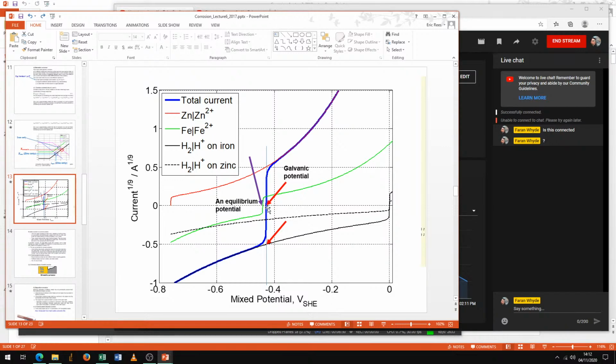That's just Le Chatelier: the ongoing net anode or net cathode process, if there is one, tends to go forwards until it opposes and reduces to 0 the thing that's causing it to happen. And the thing that's causing it to happen is a net polarization of the surface away from the galvanic potential, where there would be 0 net anode or cathode.